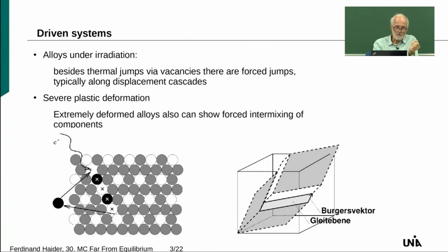What happens is that you kick out one atom and you shift forward a row of say 5 or 10 atoms. If you would not do so, you create a vacancy and an interstitial, and they would recombine directly. I also varied the size of these displacement chains. This was one way to model such systems.